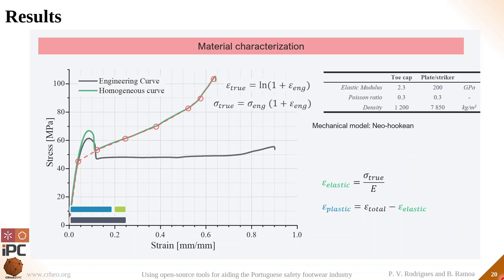For tensile tests, we follow the standard ASTM D638, which is a standard test method for tensile properties of plastics. We performed 10 tensile measurements at quasi-static velocities of 50 millimeters per minute, and we used an optical extensometer for determining the elastic modulus. The engineering curve is depicted in the image on the left with a black line. This concept of stress strain curve does not account for the variation of the cross section of the specimen during the test. And we assumed the relationships seen here to account for a homogeneous deformation of the specimen during the test, and we calculated a homogeneous stress strain curve.